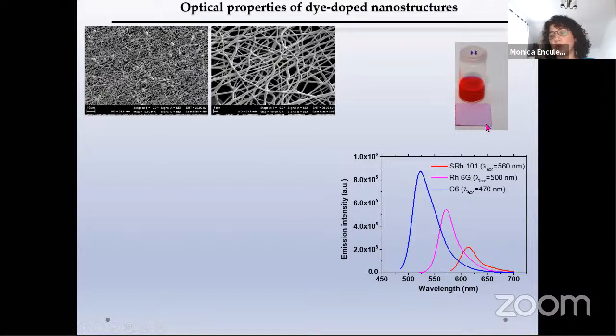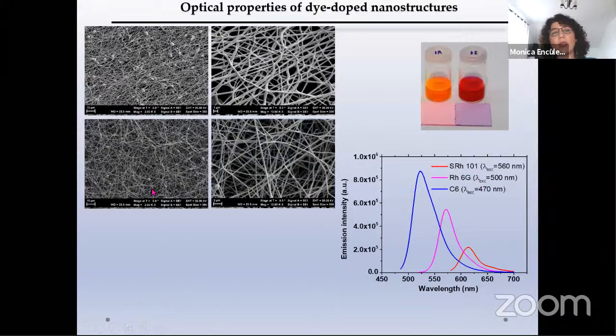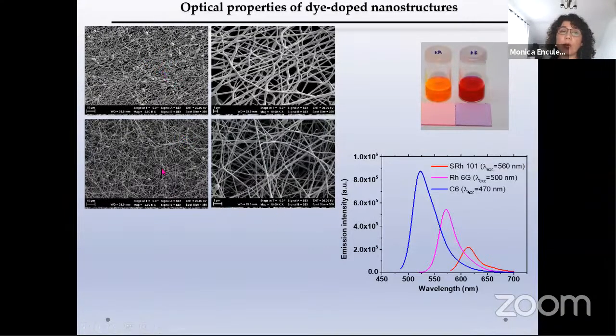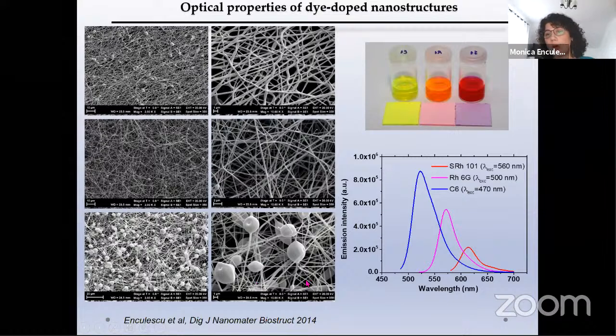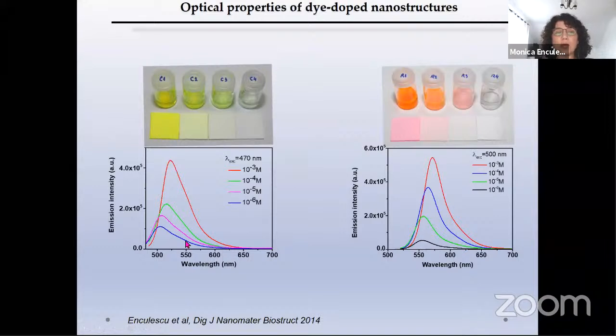It's thicker here, so more layers of fibers put one on each other. And by changing the organic dopant, the dye in the composition of these nanofibers, we can actually change also the morphologies. We can have more beads in the fibers, or fewer beads in the fibers, or larger bubbles of this type of beads on the string, as it's called, this type of morphology. So we can play with the morphological properties, we can play with the optical properties, we can play with the concentration, and in this way we can tune the wavelength at which this type of fibers emit.